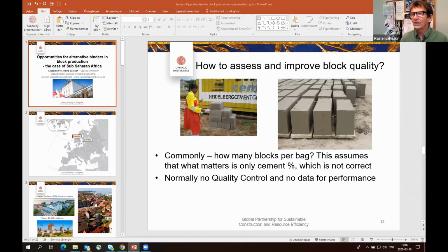We can see a big variation in the performance with the same amount of cement. But since blocks are not measured, this is often hidden. It's difficult to know that one producer actually is better than the other because you are not measuring it. And normally there's no quality control. Out of all the places, I think in Dar es Salaam, if there are several thousand block producers, there would be maybe 5 that measure the quality performance regularly.